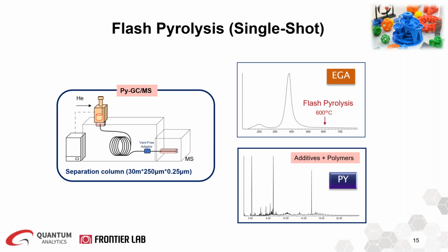The vent-free adapter allows you to change the columns without venting your MS and waiting for it to be pumped down. So it saves lots of time and increases efficiency in your lab. Flash pyrolysis then generates a pyrogram that is a mixture of all the additives, lighter, and heavier polymeric compounds. And as we mentioned, using the F-Search additive and polymer libraries, you can now analyze the compounds and pyrolytes from the pyrogram.